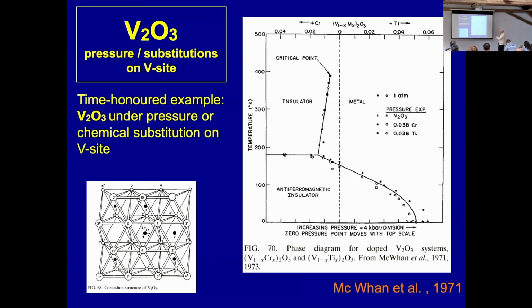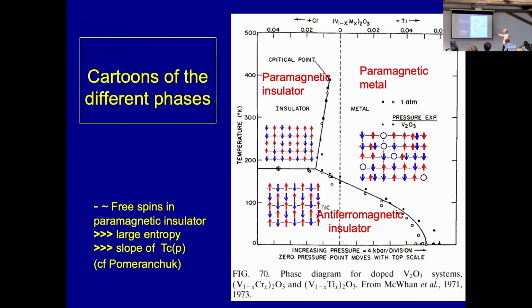And so this is just a little bit of travel back in time into V2O3 physics. Again, this material has the three phases we discussed before. This is the paramagnetic low-pressure phase, which is hole poor. This is the paramagnetic metallic phase, which is hole rich. And then eventually the system orders because it's not frustrated enough.